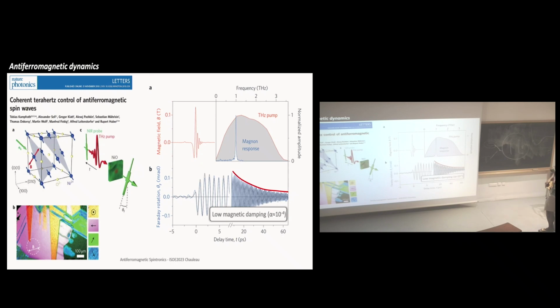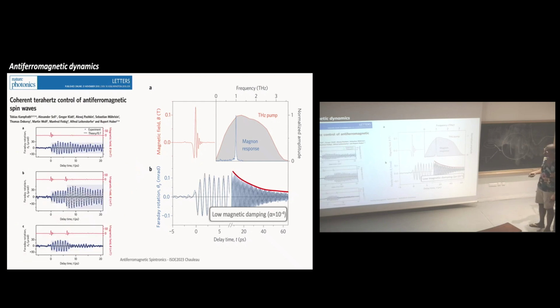So that was one of the examples. But the nice thing is that they can be manipulated coherently. And what they have performed after this, here you see the excitation. If they shine a second pulse in phase, then they can enhance the excitation. And if they're out of phase, it is destroyed. So this is really a nice piece of work, where they show that they can coherently manipulate these antiferromagnetic spin waves at terahertz frequencies.